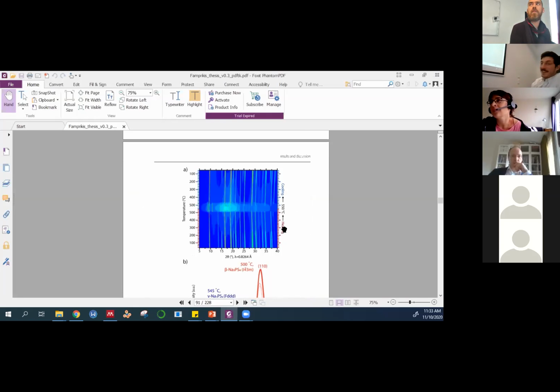Did you consider this? I did a lot, actually. I thought I was crazy when I first saw this, for like a year. There are a few ways to answer that I've come up with. One very simple one: what you're proposing, I guess, is that we have some sort of incongruent melting into two different phases of different stoichiometry, one sodium rich, one sodium poor. But I'm not sure I've ever seen a phase diagram where you can have incongruent melting and then recombine back to have incongruent or congruent solidification after. So I'm not sure that is possible thermodynamically. If we do make two phases at 550 C, we should see two phases also when we cool back down, from what I understand. I'm not sure if you agree.